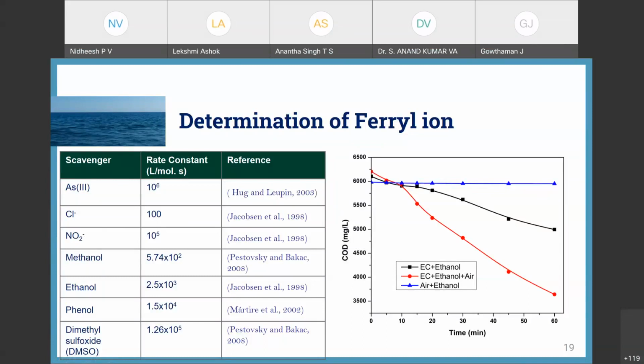So we tried other methods, like DMSO. If ferryl ions are present in the water, DMSO will react with them. So by HPLC we can find the peak. Normally DMSO will give a peak at around 24 something, so there will be a shift in the peak to around 21 something. That shift means another compound, and that is another method of finding the ferryl ion formation. Even with that, we couldn't succeed because of some issues. Again, we are trying that.